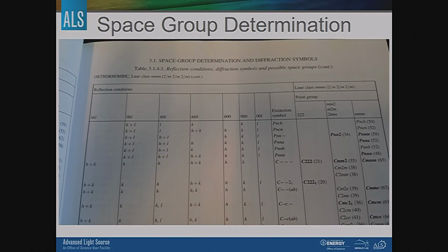If you were really invested in looking at all the possibilities that you might have for, say, an orthorhombic space group, you would want to go into the International Tables of Crystallography, Volume A. And this is only a part of one of the massive orthorhombic space group tables. And you'll see there are different kinds of extinctions listed. So this is a universal or a general condition. This is a zonal, so it only occurs in certain planes. And these are axial conditions. And these are related to different kinds of symmetry elements.